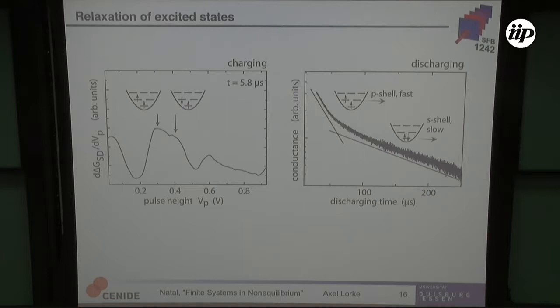And while this is again a charging spectrum where you can, with loving eyes, again see the singlet and the triplet, we used a trick to differentiate these two states better. And that trick is that this state will live much longer than this state, because nothing will keep this electron from just falling down by 50 milli-electron volts, that's the typical quantization energy, either by just emitting a photon or coupling to the phonons or you name it, most likely it's actually emitting a photon. Whereas here, this transition is spin forbidden. So you have to wait for a spin flip to occur. And this means that this state will live much longer than this state.